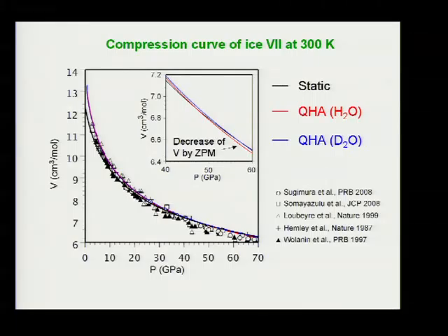At low pressure region, the agreement is excellent, but at high pressure region, our compression curve overestimates the volume a little compared to the experiment. This is because we are neglecting the tunneling effect, which is important at high pressure. And we found an interesting vibrational effect. That is, with the vibrational effect, the volume decreases from the static volume. This is an important result of the zero-point motion.